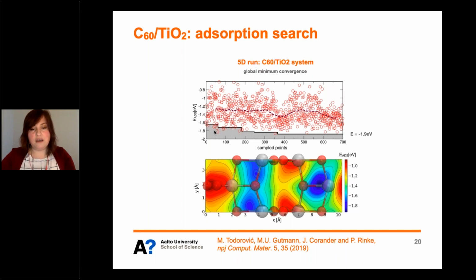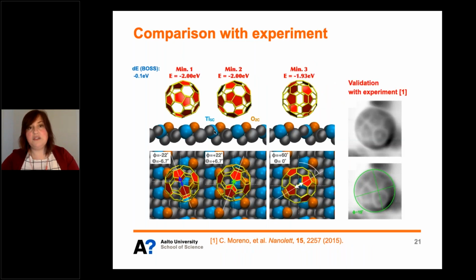Now, the best thing about these n-dimensional models is that you can cut them in dimensions that are chemically meaningful. So here's an XY map of the 2-dimensional slice through this 6-dimensional model in the XY plane of the substrate. And you can overlay this with the substrate atoms and clearly see that the global minimum is found near this 5-fold coordinated titanium atom, which is what is expected from the chemistry of the surface. So this is interpretable chemical insight we get from machine learning.